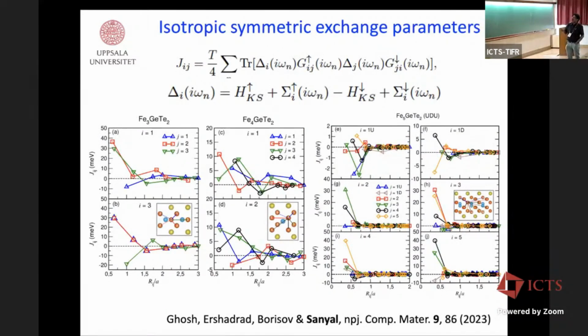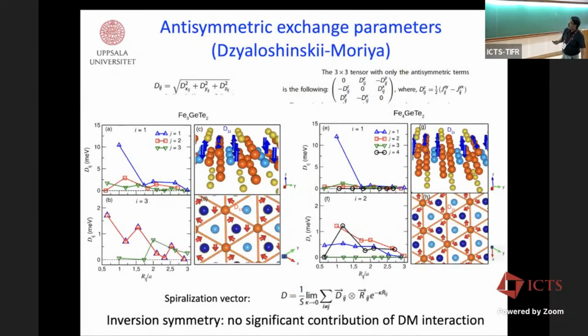I will not spend much time here. There are a lot of plots here, many things to say, but these are all calculated within dynamical mean field theory. You see lots of antiferromagnetic exchange interactions happening. If you compare DFT and DMFT, you'll see that there is a renormalization of the exchange parameters happening. An interesting thing is that the Dzyaloshinskii-Moriya interaction parameters can also be calculated, as I said, as a function of distance between these atoms. In this case, this interfacial DMI can be easily calculated also in this way.